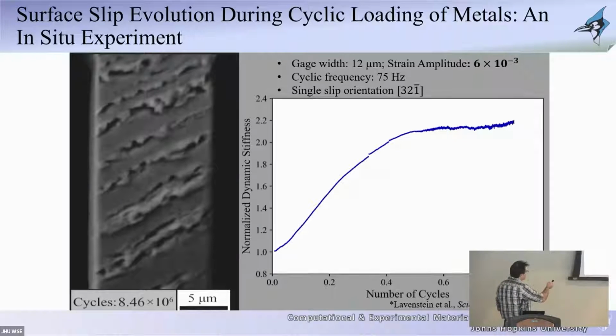And it's only when that first event happened with an extrusion, that's really about here, when the curve started becoming nonlinear. And eventually that leveling off, that's what is known as saturation, again in the world of fatigue. The leveling off is when there's not a significant amount of apparent change in the surface roughness of the sample, and there's no apparent significant amount of hardening that is continuously building up in the material either. So first, it was quite unique in the sense that this experiment basically allowed us to see the nucleation and the evolution of these slip bands.